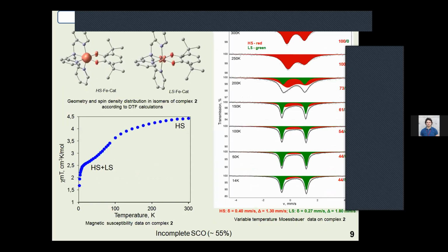Unfortunately, we were unsuccessful in obtaining single crystals suitable for X-ray diffraction for complex 2. Nevertheless, the geometry of complex 2 was obtained from the DFT calculation. It should be noted the obtained structural data are close to compound 1.